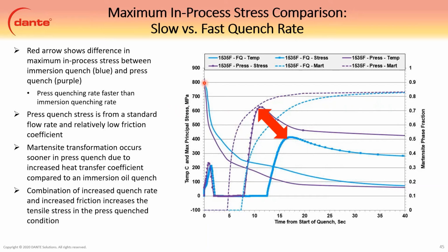But we can show all of that, right? So these two lines are temperature. The dotted lines are martensite transformation. And then these squares are the stress. So we can see where it comes from, right? Here's your martensite transformation, but your stress, and this is all just at the surface. So you have to keep in mind that it's not the surface martensite transformation that's causing this stress. It's subsurface martensite. So you really need a couple more plots on here to really drive home what the cause is.